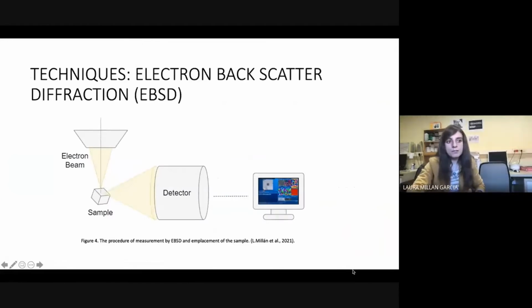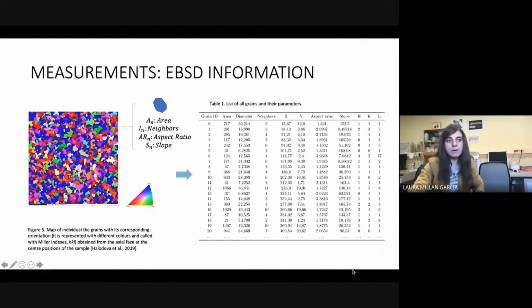After, we measured the surface in the axial direction by electron backscattering diffraction. This technique offers us a map of grains and information on the microstructure and the grain's orientation. It is represented with different colors, colored with Miller indexes. It can also provide a list of grains and their features.